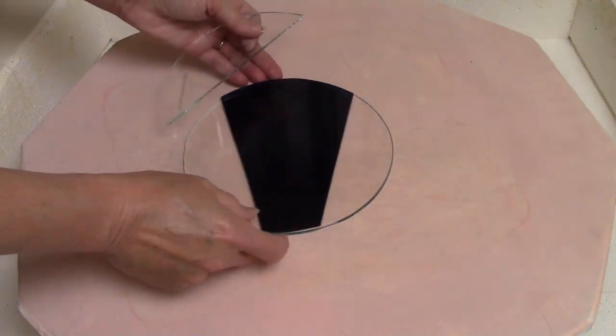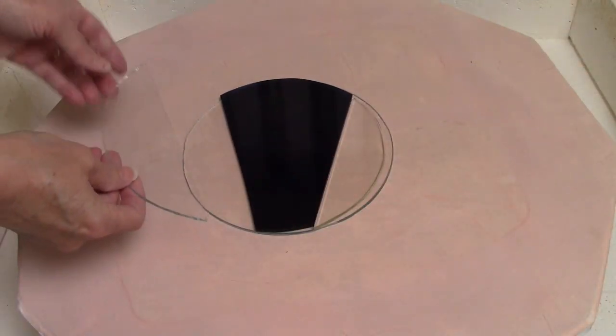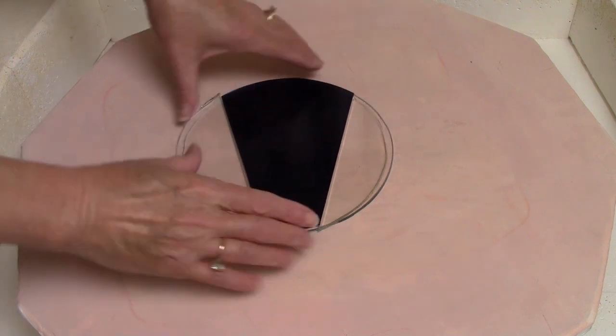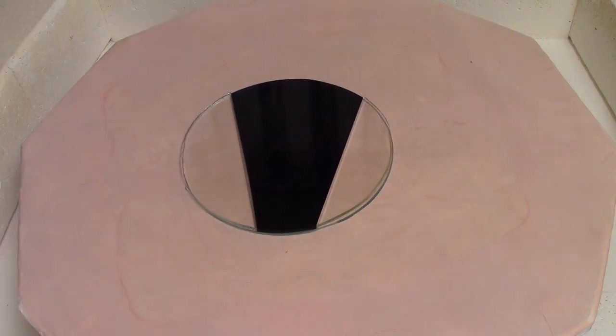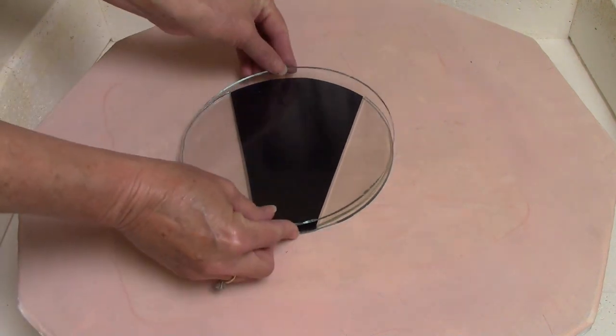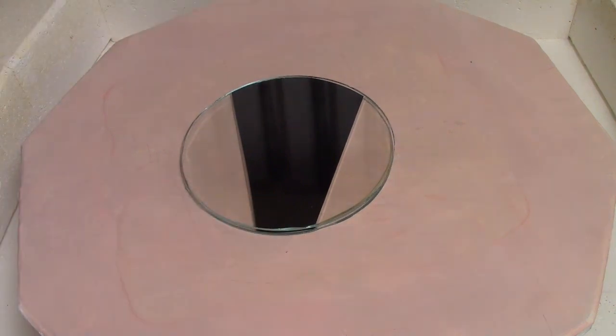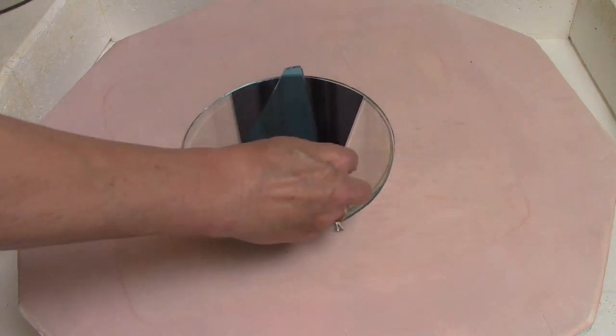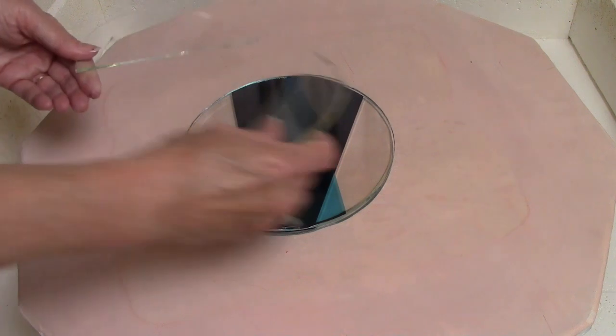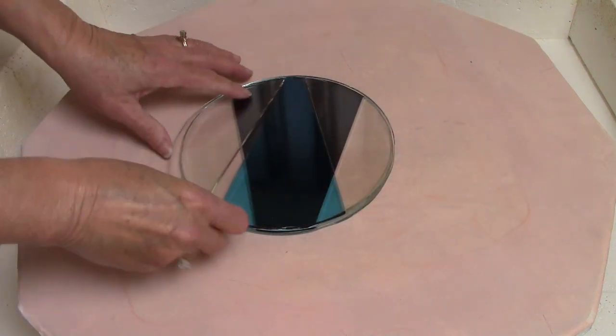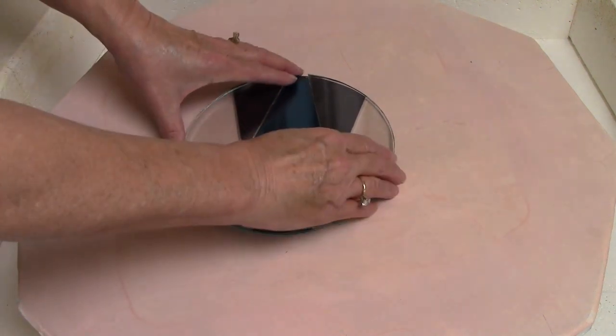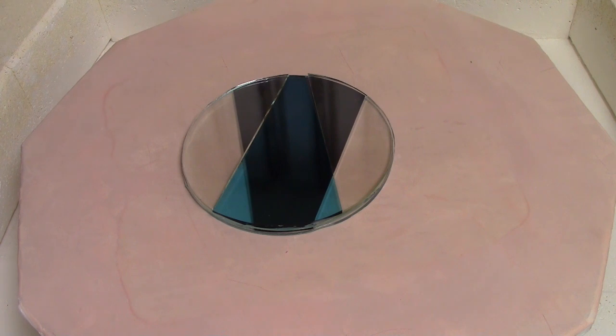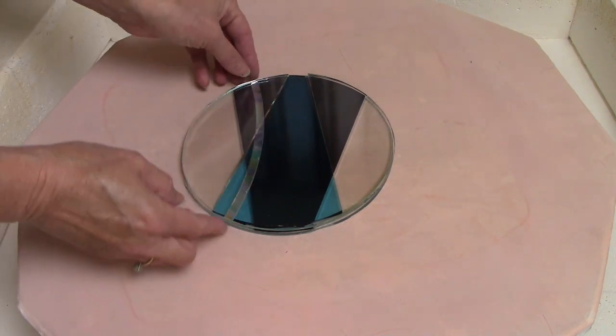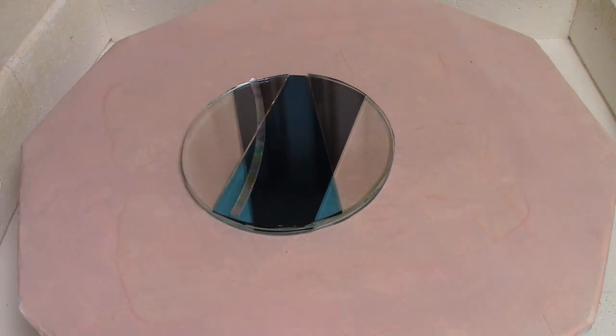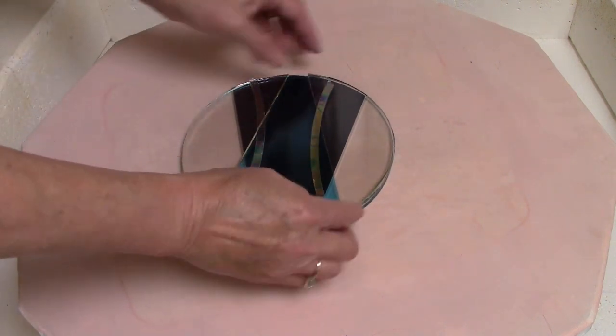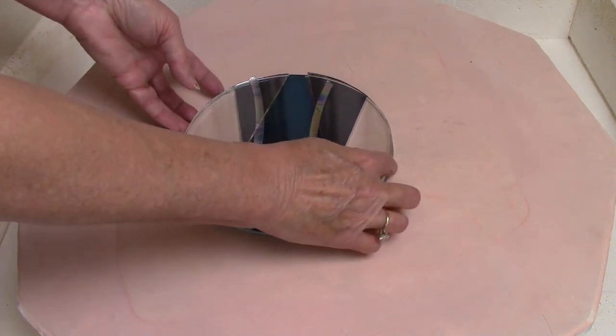The cool thing about a dropout vase is you can get a shape and a style that you otherwise cannot create in the kiln. To make one, you stack 4 or 5 or even 6 layers of glass together, and then you fire it to a full fuse temperature to create one big, thick, heavy blank. Here I'm creating a very simple design by having a pale blue, like an aqua blue on one layer, and then a steel blue on the other. Then I'm including some dichroic pieces.